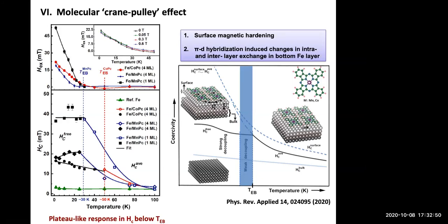So what we're looking for to be able to see exchange bias is primarily, computationally, if some molecule shows that you can enhance spin-orbit effects at the surface through the interaction of the interface states. And secondly, if you're able to demonstrate from DFT or computational studies, by doing spin-polarized non-collinear DFT calculations, that the interlayer exchange coupling between the surface and the layer below it is reducing drastically, then this is a very good indication that the molecule will show exchange bias. I see.